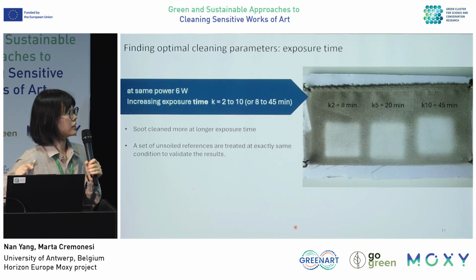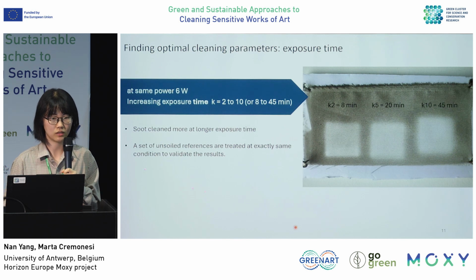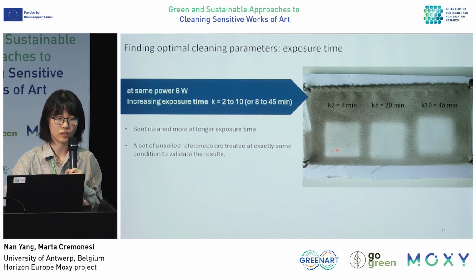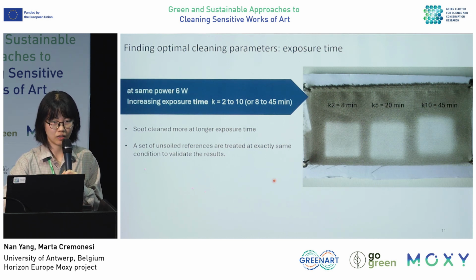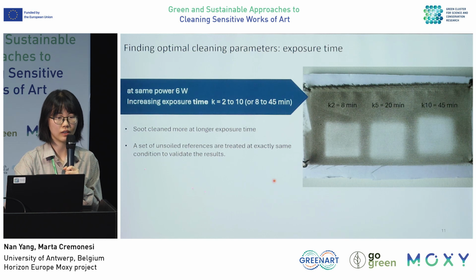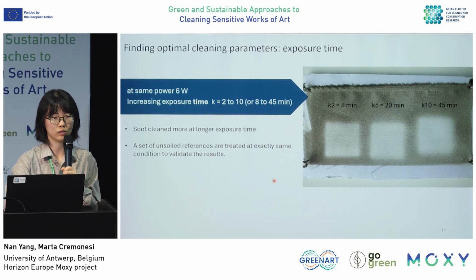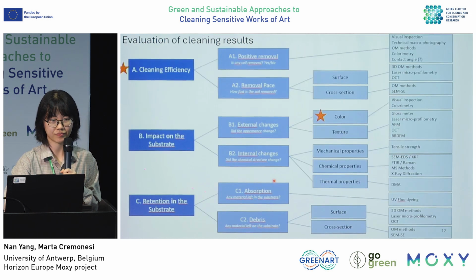The same experiment was done for the exposure time. We increased the exposure time from 8 minutes to longer, within 1 hour, just to control that it will not take so long. And the same experiment was also done on unsoiled, pristine samples, just to validate the results, especially focusing on damage to the substrate.